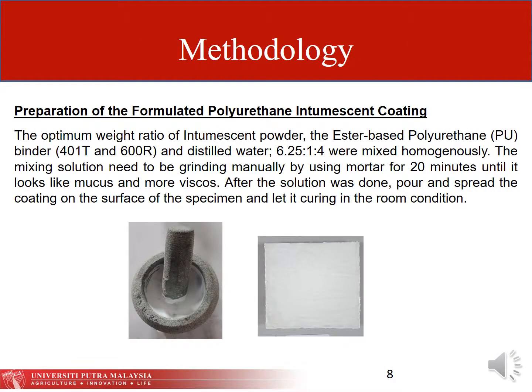Coming to the methodology part. Preparation of the formulated polyurethane intumescent coating. The optimum weight ratio of intumescent powder, ester-based polyurethane binder, and distilled water is 6.25 to 1 to 4. It was mixed homogeneously using a mortar for about 20 minutes until it looked like mucus and more viscous.